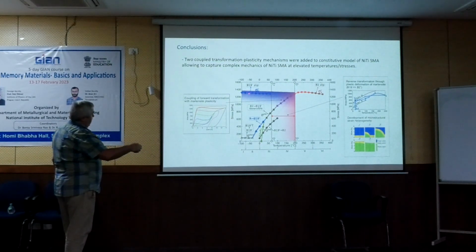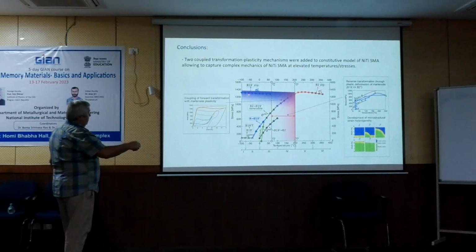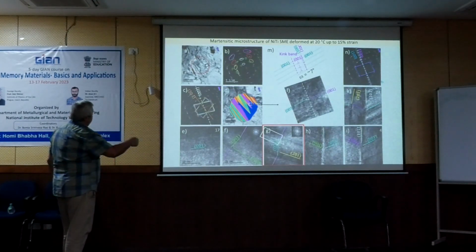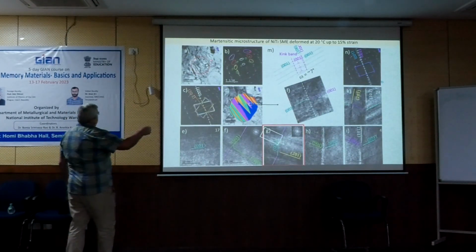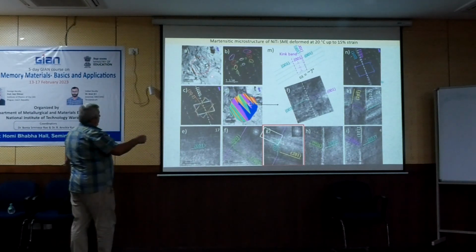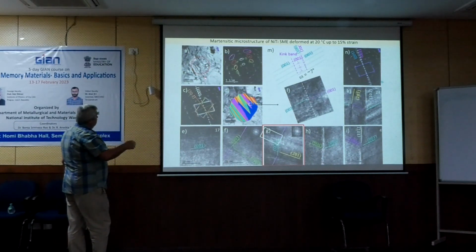This is about this line. So when we deform and cross the yield point, the martensite deforms plastically, and I discussed here that even upon cooling under stress it will deform plastically. And when we look into the microstructure, we see such kind of microstructures where there are individual deformation bands, and depending on the orientation they are now painted. So there is such kind of microstructure.